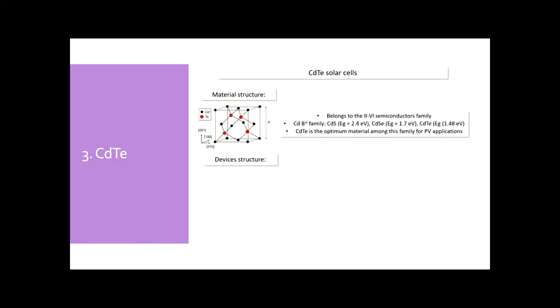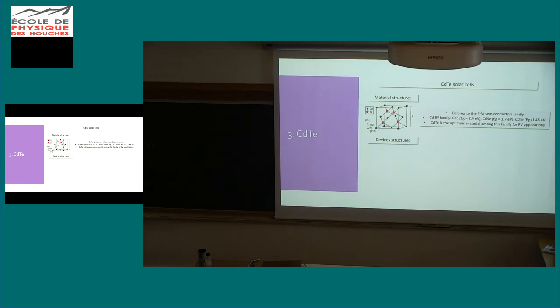This is the structure of cadmium telluride. It's a cubic structure. As you can see, it's a zinc blende structure. It belongs to the II-VI semiconductors family, which is technologically a very important family. And normally in the family you have cadmium sulfide, cadmium selenide, and cadmium telluride. And cadmium telluride in terms of band gap is the best suited for photovoltaic application. So that is why we are using cadmium telluride and not the others. Cadmium telluride is the optimum one in terms of band gap.